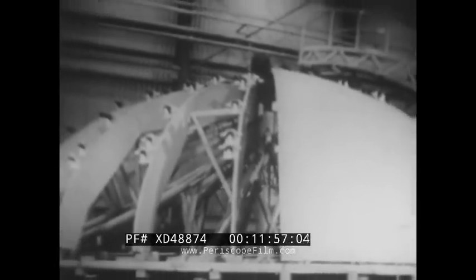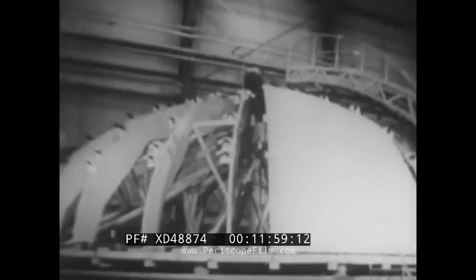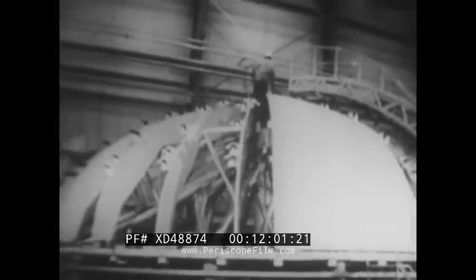Assembly welding jigs are used to precisely locate the gores. They are then welded using a North American developed automatic skate welding technique. The fabrication of a single bulkhead requires a minimum of 300 feet of weld bead, which must be as perfect as possible. The welds are then inspected for voids by using X-rays. Following that, they are checked for leaks in a hydrostatic test and undergo a helium leak test.